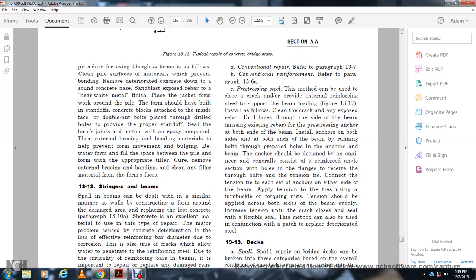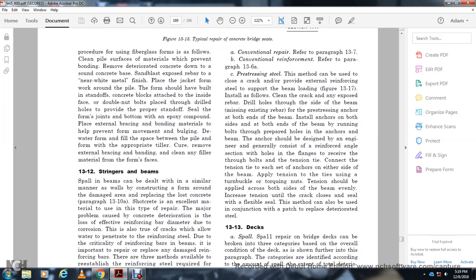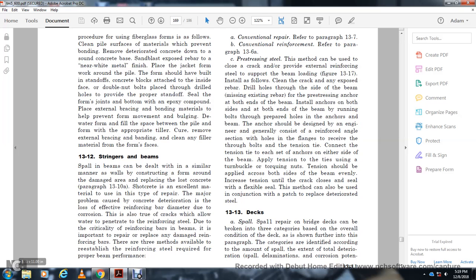Alright, 13-12, Stringers and beams. Spalling of the beams can be difficult. Forms can be constructed around the damage after removal of the loose and lost concrete. Shotcrete is an excellent material for this type of repair. The main problem with concrete deterioration is the effect on the reinforcing bar, the loss of diameter due to corrosion. Cracks allow water to penetrate the reinforcing steel, damaging critical reinforcing bars in the beam.